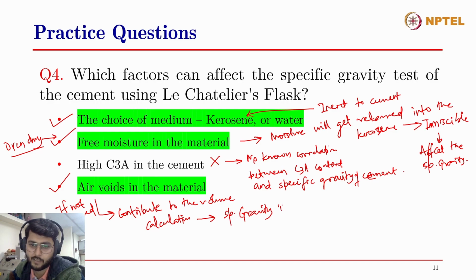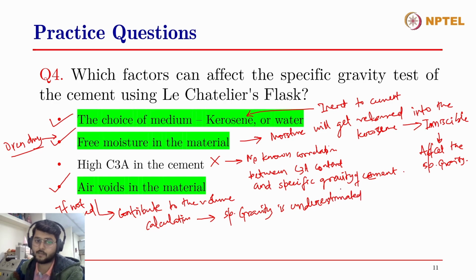Specific gravity is in fact underestimated, because if there are air voids trapped within the kerosene, then there will be a higher volume change with a given amount of material. So the mass to the volume ratio will be lower. We need to release these air voids so that we get the accurate specific gravity. So the mass to the volume will be as accurate as we know, and therefore the specific gravity will be lower if there are air voids entrapped within the system.